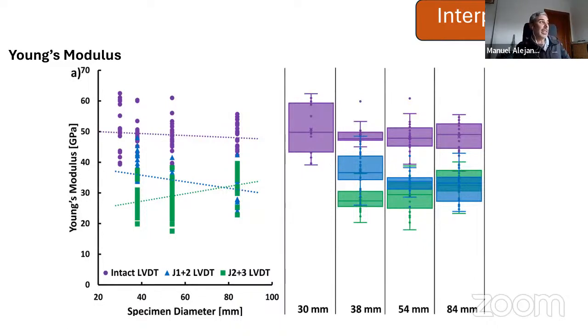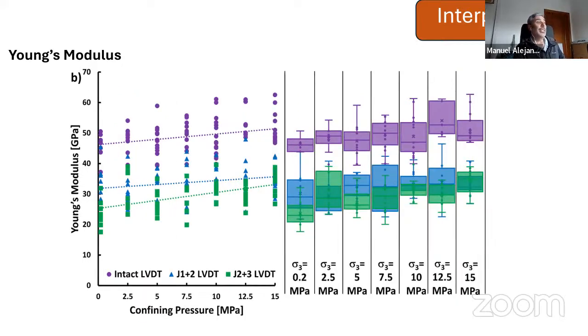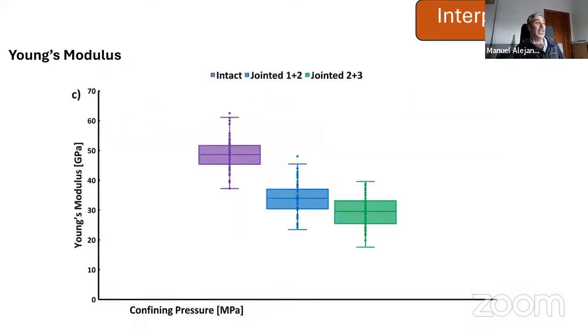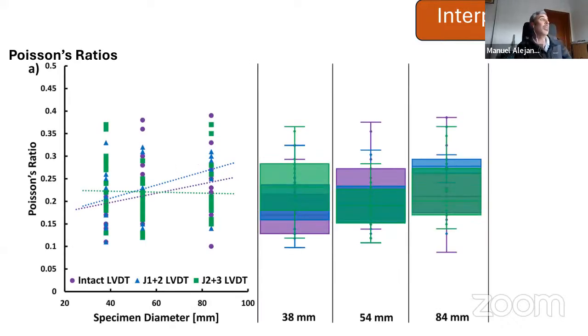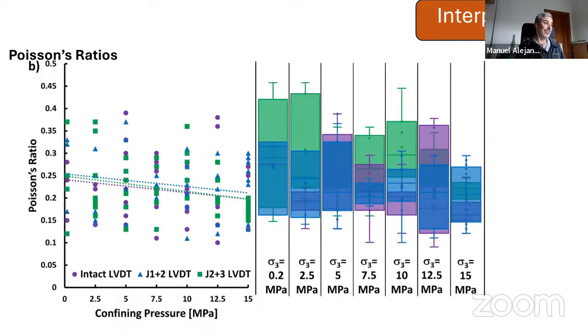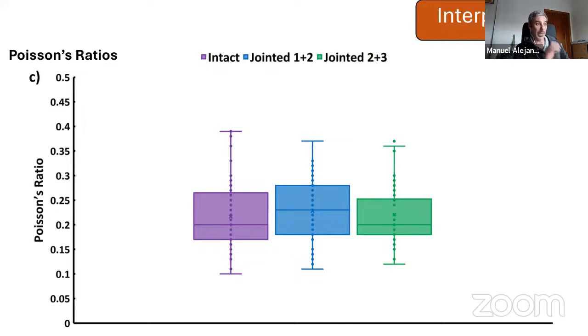For the elastic parameters, we observe that the Young's modulus with the diameter more or less stays the same. There is no variation or a slight tendency to decrease. With the confining pressure, it tends to increase, but the clear trend is that when we increase the level of jointing, the Young's modulus tends to decrease. The Poisson's ratio tends to be more or less constant with the increasing diameter. It has a slightly descending trend with the increase of the confining pressure, and it seems to stay constant with the increasing level of jointing.